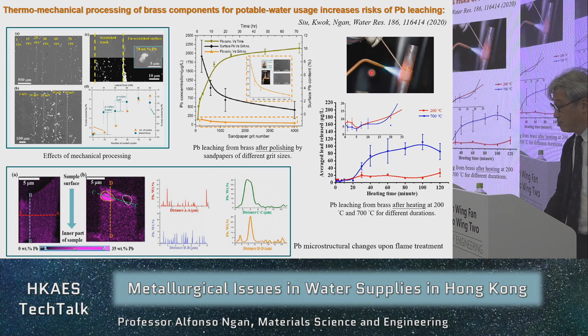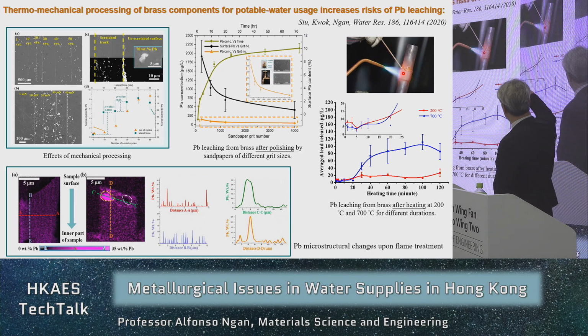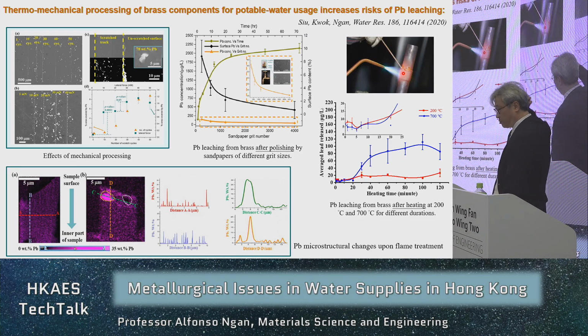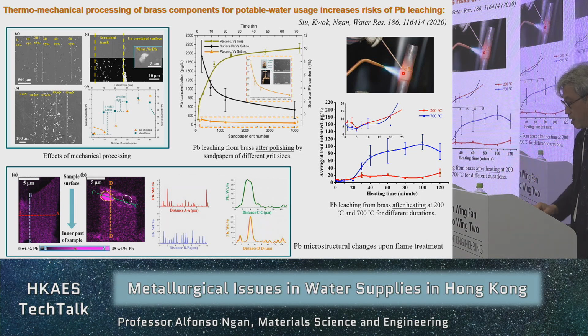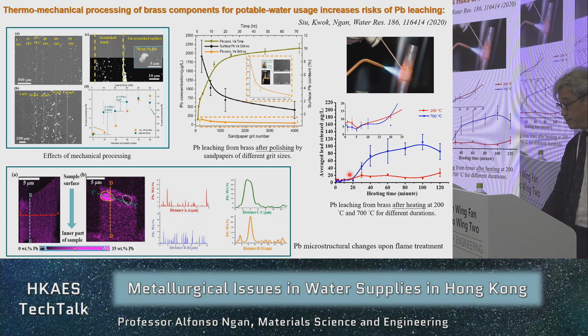And not just mechanical machining. As I said, you can also heat up the brass as you do soldering or brazing. So in the laboratory, we use two temperatures to simulate these two processes: 200 degrees Celsius to simulate soldering, and 700 degrees Celsius to simulate brazing. We found that after heating up the brass and then immersing it into water, lead again will leach into the water, okay? Of course, it will leach more if we heat up the material for longer durations. So the thermomechanical processing is an important factor leading to lead leaching.